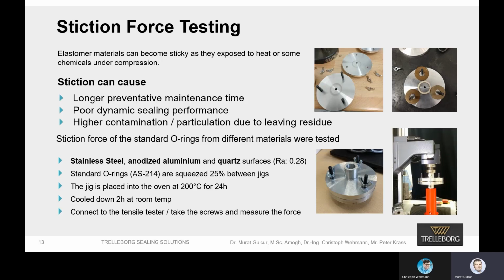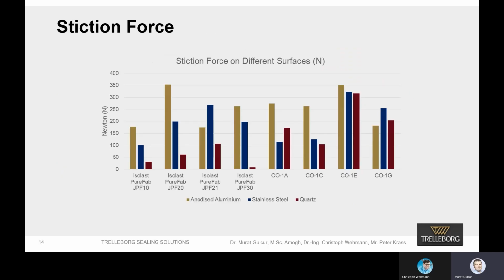So we are using this stiction test method, which I'm going to talk about very briefly. We have either stainless steel, anodized aluminium, or quartz surfaces that we do the test on. So we take two of those surfaces and we squeeze the O-ring by 25% between those jigs, and then we put it in the oven at 200 degrees for 24 hours. And then after resting for 2 hours, we connect it to our tensile machine and measure the maximum force that we get in order to separate those plates from each other. So, similar to the outcome of plasma testing, every material is different, as you can see, this is some of the data we have.